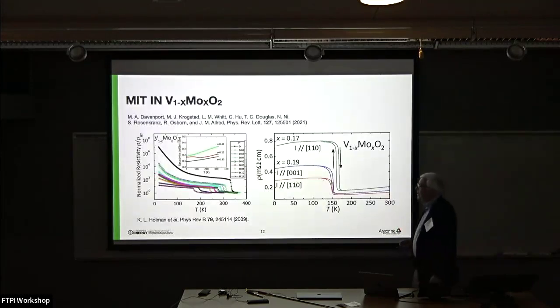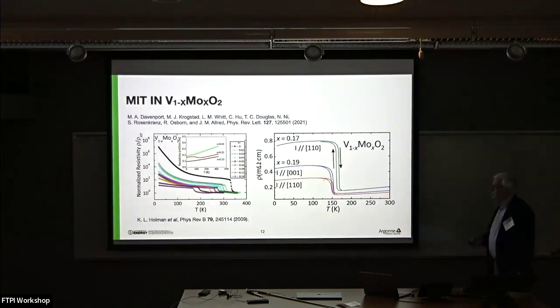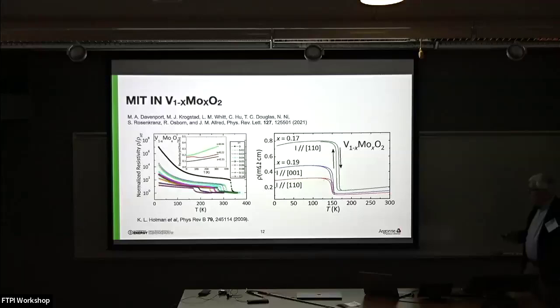So Bob Cava's group were interested in what happens if you dope with molybdenum, and you can suppress the transition a long way. It persists up to quite high concentrations of molybdenum. But in particular, if you go out to 17% and 19% here, you see you still get a first order electronic phase transition. It's now more metal to metal, but nevertheless you have these first order phase transitions at 17%, another one at 19%, etc.